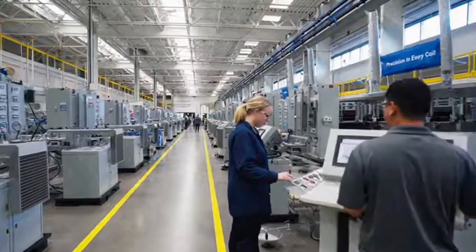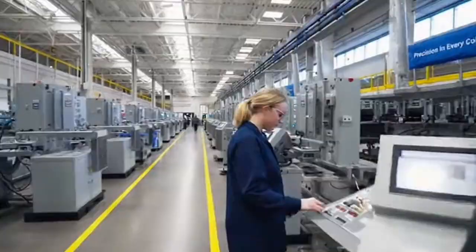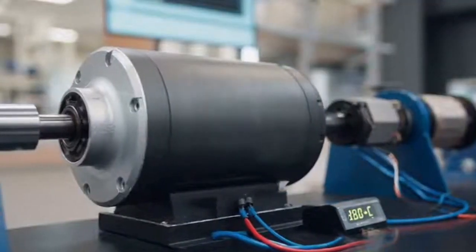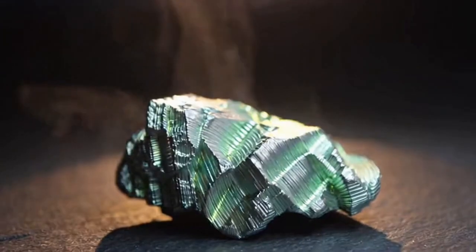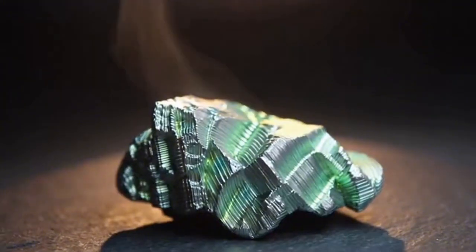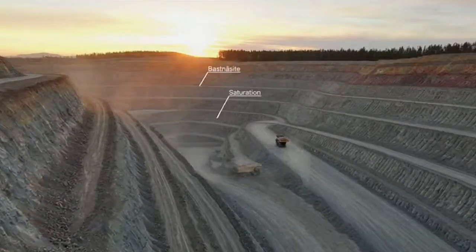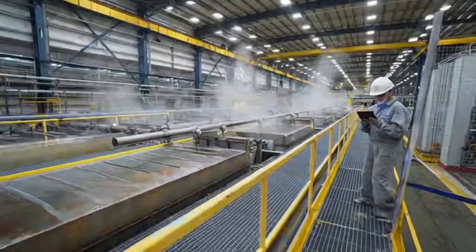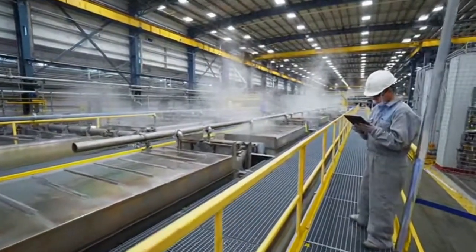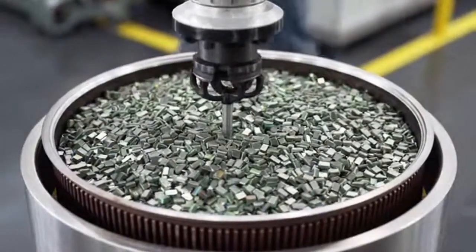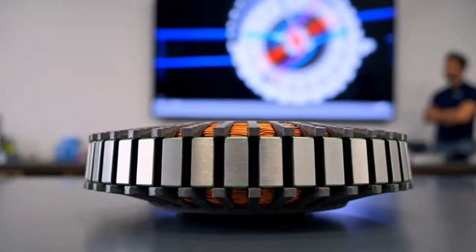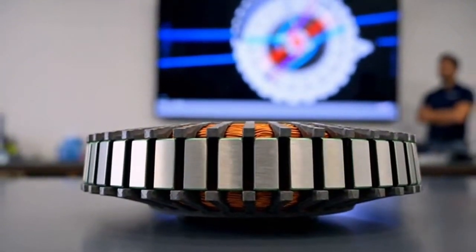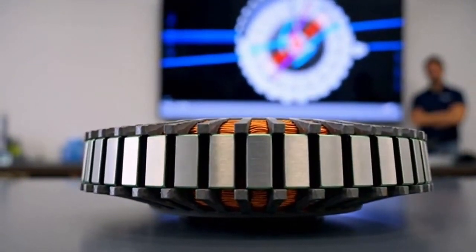Recycling, to be useful here, has to be described without romance. Inside a magnet house, in process scrap is a bankable resource. Hydrogen decrepitation turns whole rejects and machining swarf back into feed with minimal drama. Oxygen and carbon are watched like hawks, the blend of neodymium and praseodymium is preserved rather than unscrewed, and the loop closes in days, not months.